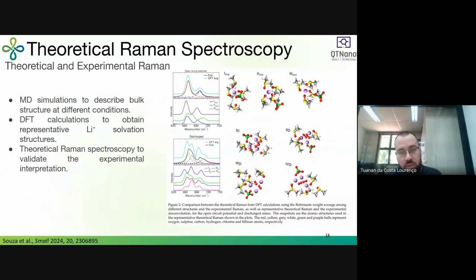So to try to avoid this problem, we did the MD simulations for the charged and discharged battery. From the MD simulations, we extracted representative solvation shells, and we submitted the solvation shells from the MD simulations to the DFT calculations to improve the description of the atomic interactions within the solvation shell. Then, using 20 solvation shells for each one of the systems, we calculated the theoretical Raman. If we look here, we have in cyan the DFT average for the Raman spectroscopy for the charged battery, and in black the experimental data. And if we compare, we have a really good match between the experimental data and the DFT simulations.